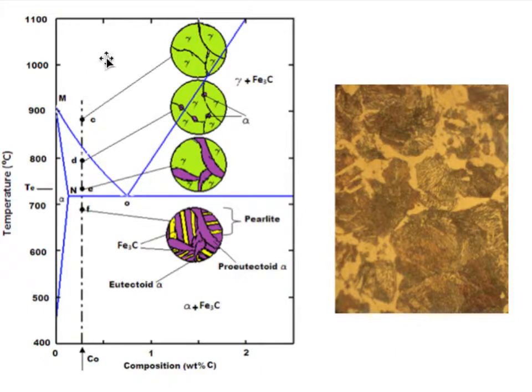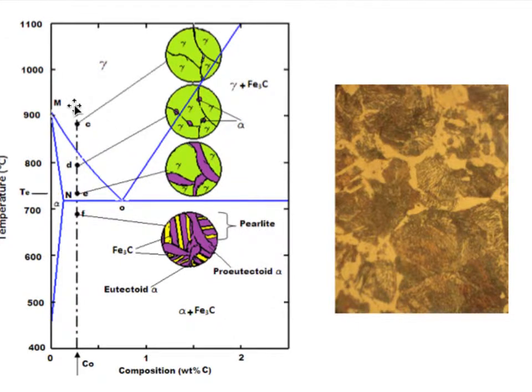And we start up here in the austenite area. It means that we have one phase, the one-phase austenite with grain boundaries. And then we start lowering the temperature. When we come down to this line, we start to precipitate ferrite as we come into the two-phase region, ferrite and austenite. The ferrite will precipitate preferably in the grain boundaries, as the crystallographic structure is disturbed, and we will save some energy if we precipitate the secondary phase in these areas.